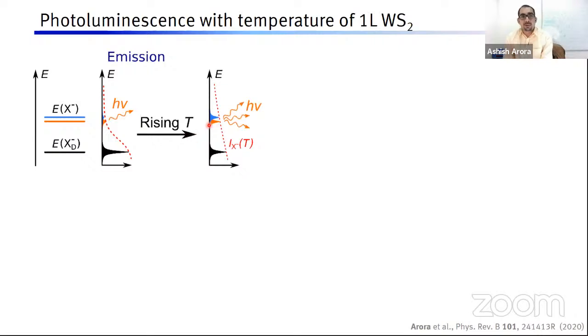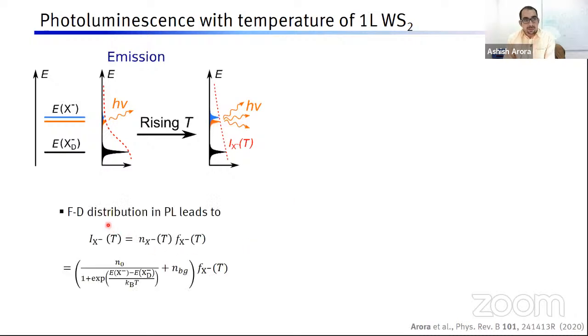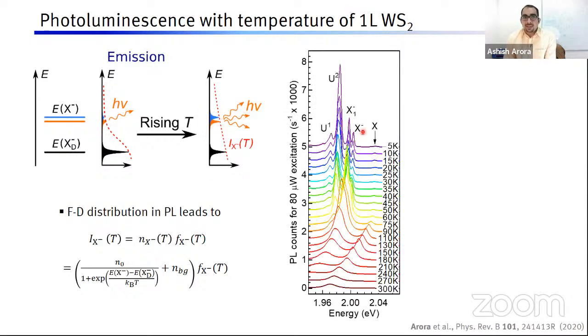But when we raise the temperature, the emission from the material should increase, because you are redistributing these trions to the higher energy bright states. So the intensity of the bright trions can be written as the number density of bright trions multiplied by the oscillator strength of these trions. Let us see what happens in experiment. We have these two trions, and we raise the temperature. We find that the trion intensity increases with temperature, and then it starts to reduce.